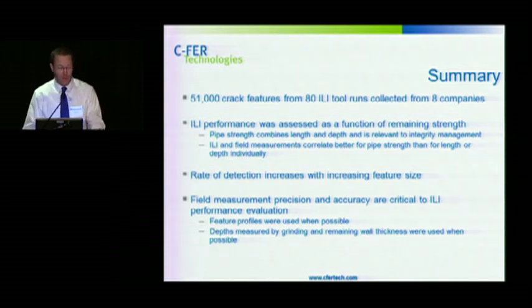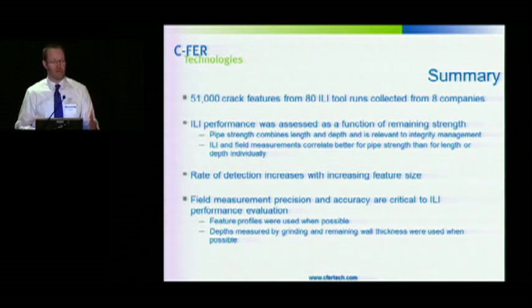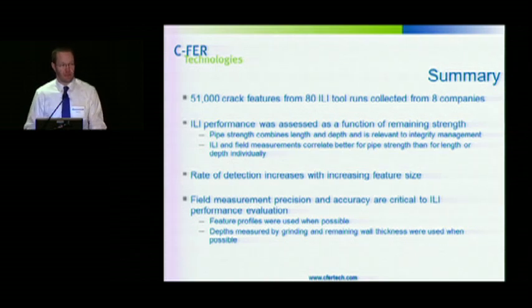A couple of the reasons why, though, were that the pipe strength combines length and depth and is also relevant to the integrity management process. We could have done a similar thing where we were tracking performance with something to do with area, but what we found is that length or depth individually was not enough to characterize the ILI performance, so we used remaining strength.